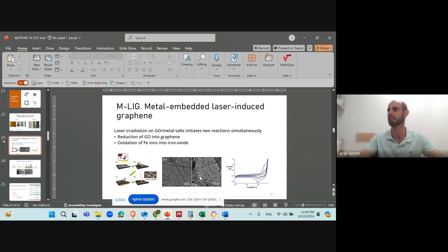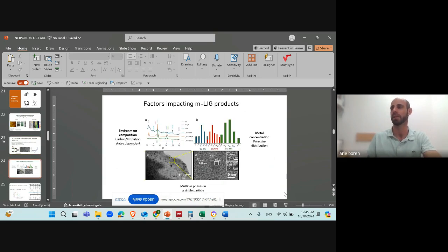This is iron oxide nanoparticles. And you can clearly see in a CV the redox peaks. Remember that flat CV that we saw for only carbon? Now with oxygen, we see clearly the redox peaks because we have redox active material there. And this really opens a lot of opportunities, almost endless options of what you want to do with these materials once you introduce the carbon with other materials. Okay.